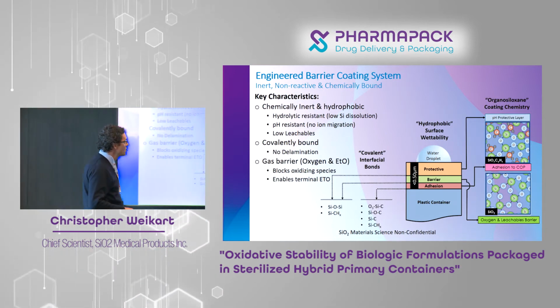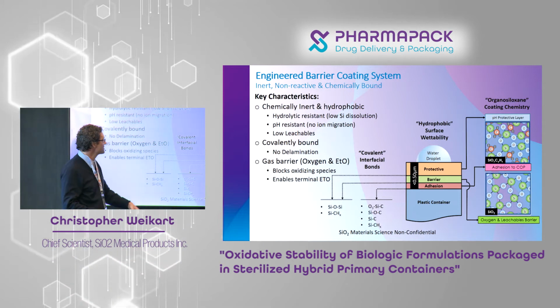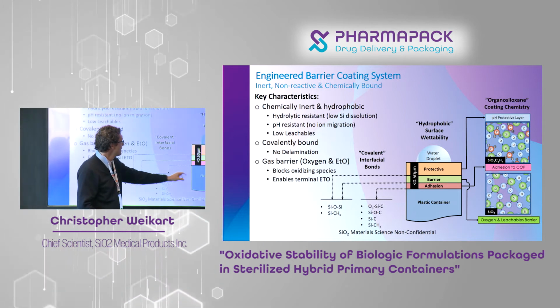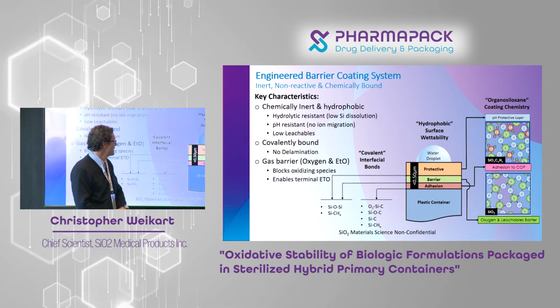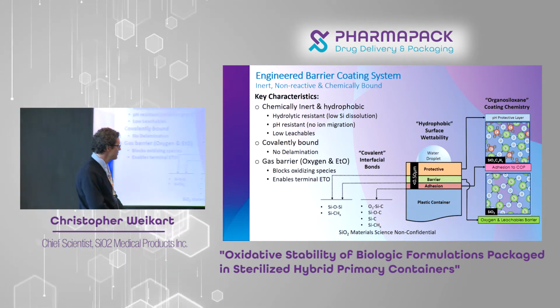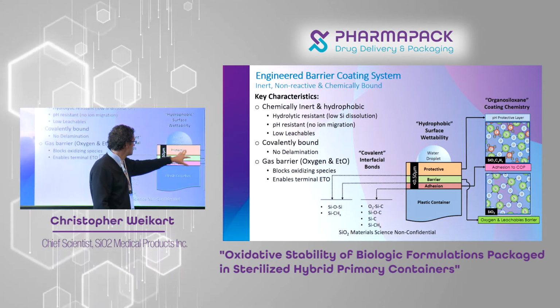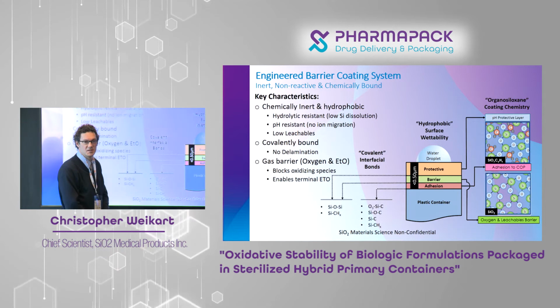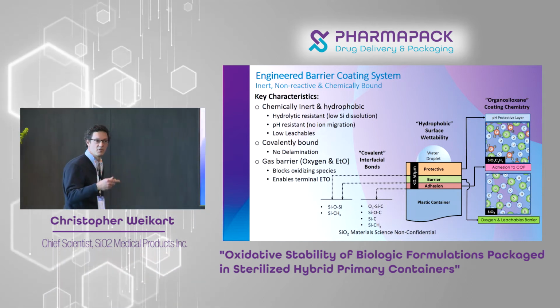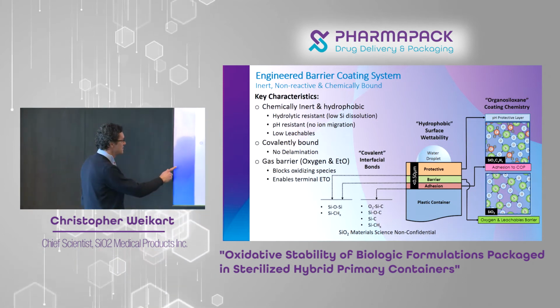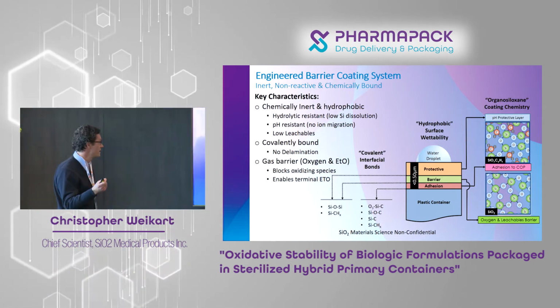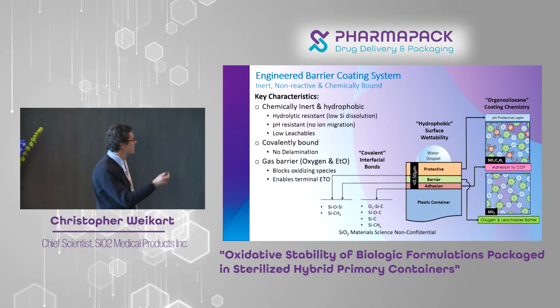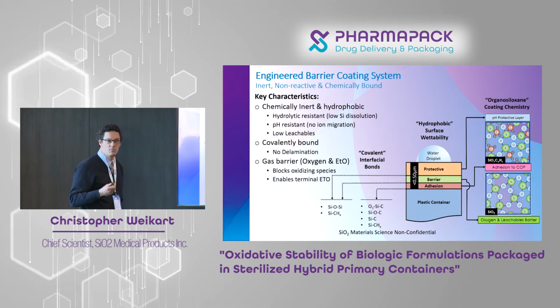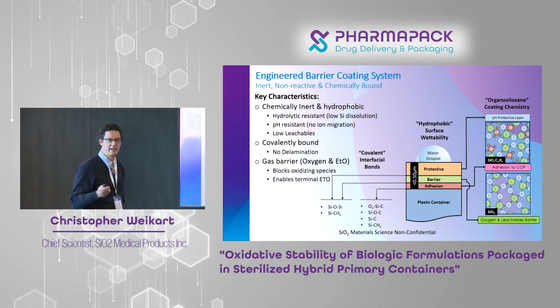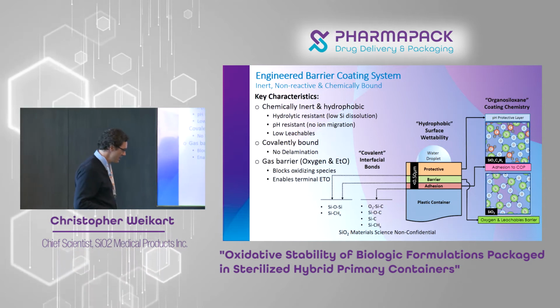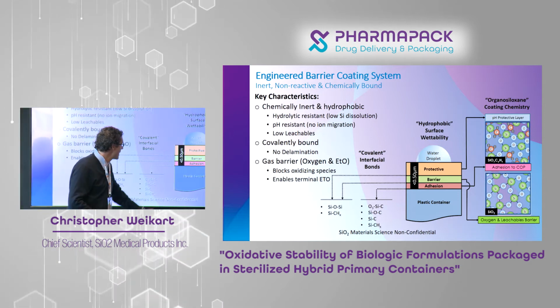So the coating architecture and chemistry, this is basically a snapshot of that. You can see we have a 3-layer structure. The chemistry over here you can see in an atomic visual sense. You can clearly see we do have a pure silica layer in the middle, and then the 2 other layers are silica but also have carbon built into them. The presence of the carbon is really essential, not only for binding the entire stack to the polymer through very covalent bonds with the polymer backbone, but also for protecting the silica layer. Without any protection, the silica would dissolve like any other glass. So you have to protect it. And it's maybe hard to tell, but this entire stack is about half a micron.